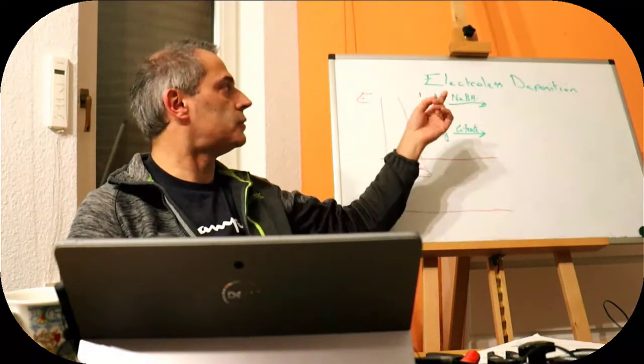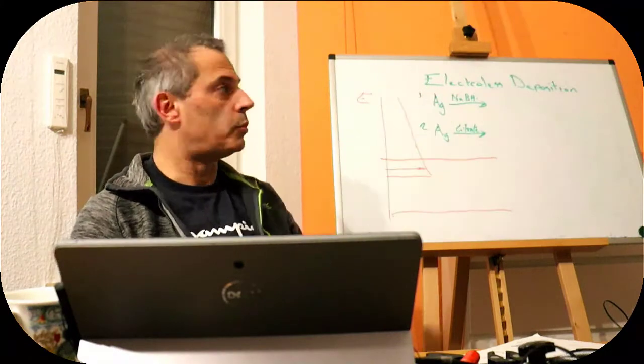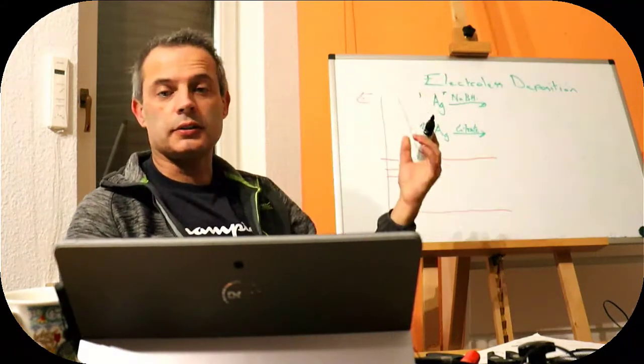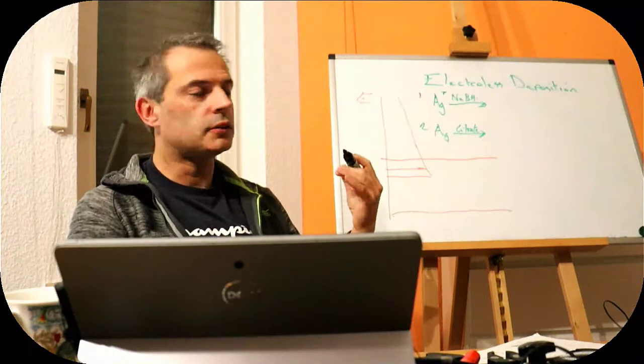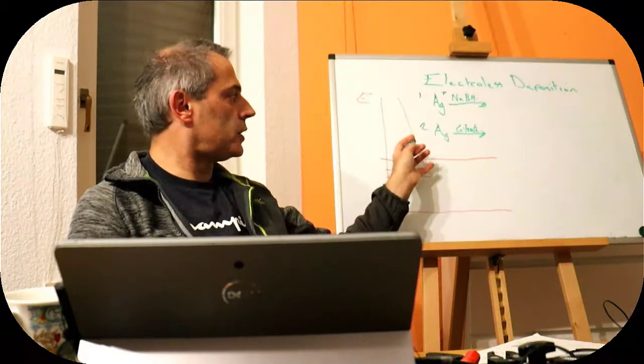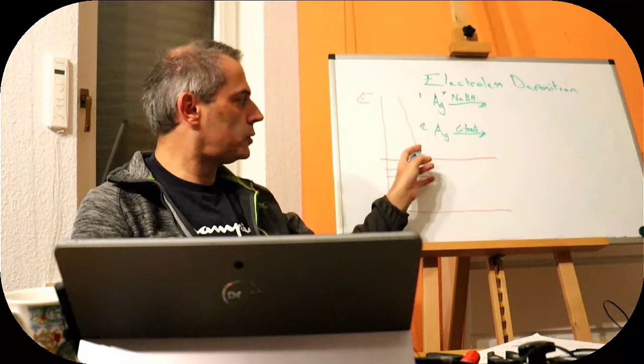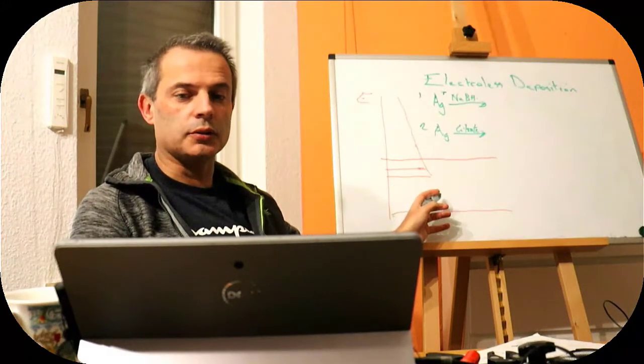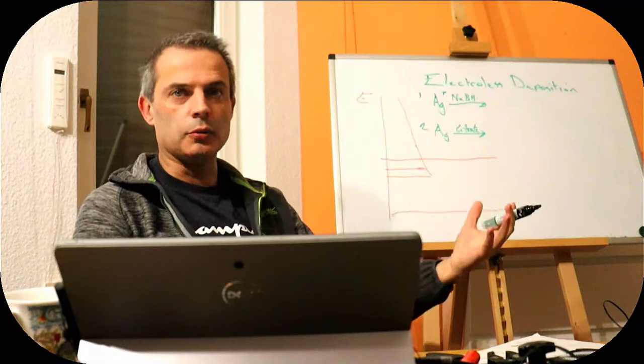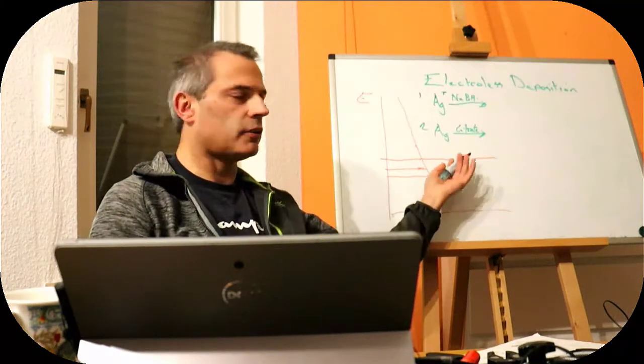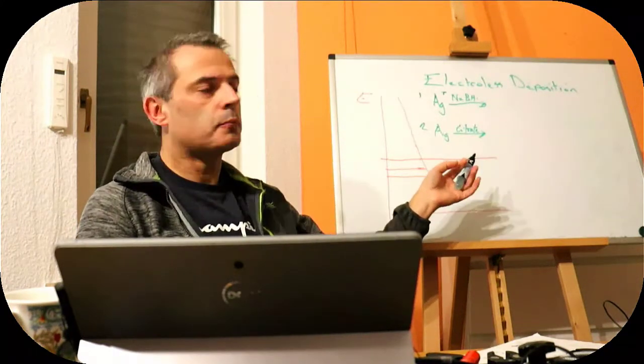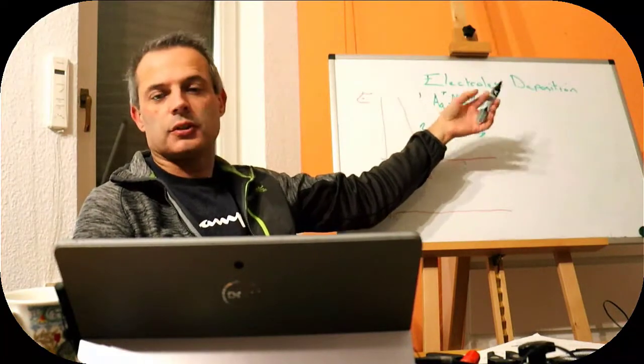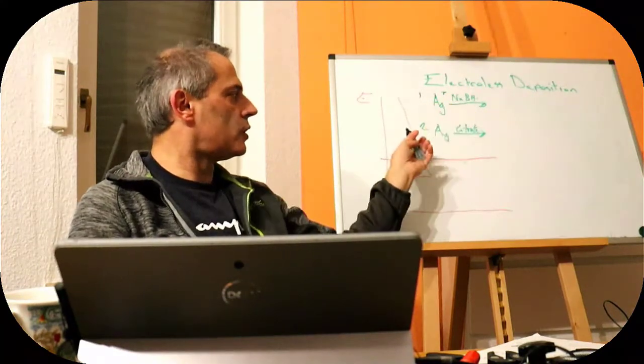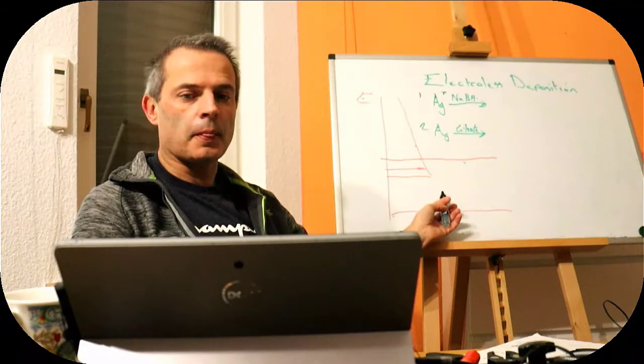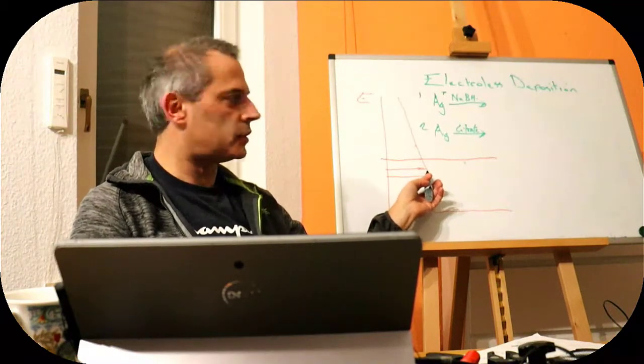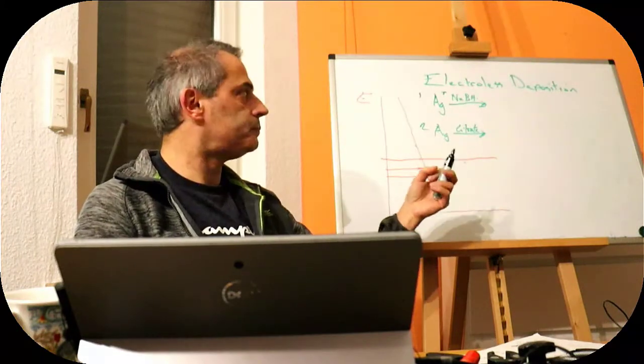So what you will see is if we have silver plus obviously, and we want to make silver 0 nanoparticles, then we have to make them fast because we have to pass this nucleation point. We have to pass the saturation point and pass the nucleation point very quickly so that we make new particles, and we want to get back very quickly to our equilibrium. So we reduce it with something very strong like sodium borohydride, which brings it right down here, and that will obviously cause it to pass this point here where it will generate new nuclei.